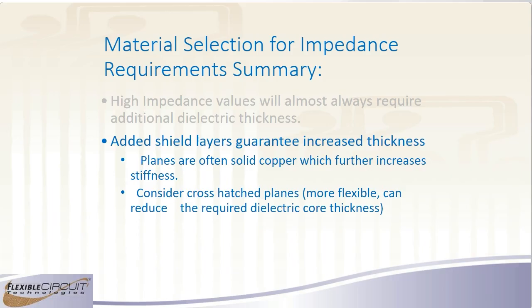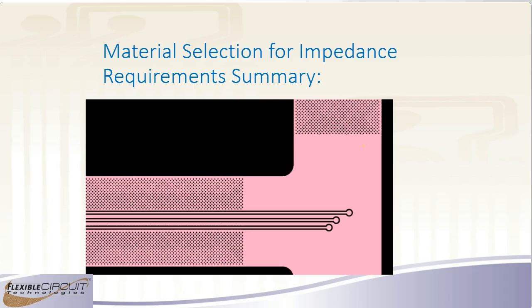One thing to consider is to use a strip or a crosshatch pattern for your planes. And what I mean by that is to basically take out a dot pattern or a diamond pattern or something in your plane layers, and that will allow you to get a little bit more flexibility. And the other advantage is by removing a portion of that return path, you're elevating the impedance without spreading the conductors or the planes out and separating them from the internal layers. And so this allows you to get elevated impedance without increasing the thickness significantly. And most of the impedance calculators nowadays will have this as an option to go in and put in a crosshatch plane pattern and give you the impedance that you're going to get.